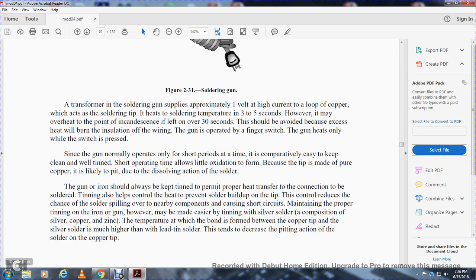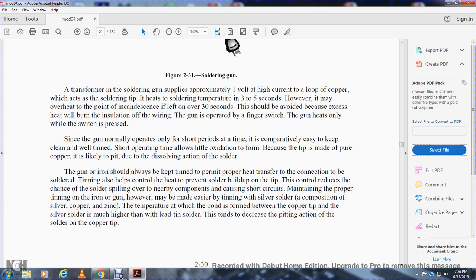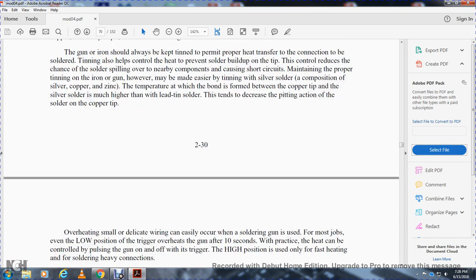Maintaining the proper tinning of the iron and the gun, however, may be made easier with the tinning of silver solder. The composition of silver, copper and zinc means the temperature at which the bond is formed between the copper tip and the silver solder is much higher than with lead-tin solder. This tends to decrease the pitting action of the solder on the copper tip.